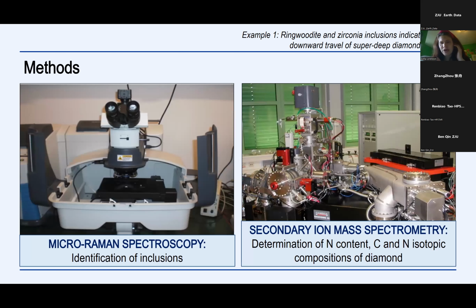To carry out this characterization, we performed mainly two different types of analytical techniques. The first one was micro-Raman spectroscopy, which, as I said before, we use for the identification of the inclusions in our sample. The second analytical approach was secondary ion mass spectrometry. I didn't talk about this technique because we usually do not perform it at the University of Padua. These analyses were carried out in collaboration with the University of Lorraine in Nancy, and this technique allows us to determine the nitrogen content in our diamond.